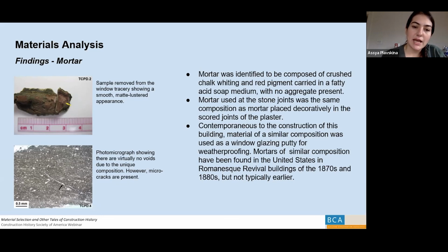What's particularly interesting is that in the mid-19th century, a mix of very similar proportions was used in construction, but as a weatherproofing material for window glazing putty. Mortars of similar composition were found in the United States. We have seen examples of it, but not until the 1870s or 1880s in Romanesque revival buildings. This is definitely the first example that we and other experts have seen of this particular mortar mix being used within joints. The appearance of this mortar, due to the lack of aggregate and the binders, is sort of matte lustered, very smooth, obviously, because there's no aggregate in it. It's in pretty good condition as a result. Where it remained, it was in good condition.